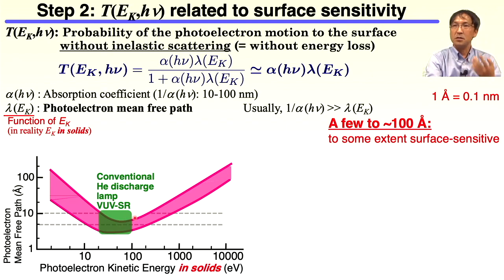This means that the surface electronic states can be obtained by the VUV photoemission. This is rather unhappy for the scientists who want to probe the bulk or buried layer electronic structure of solids, where the surface states are often highly deviated from the bulk ones.